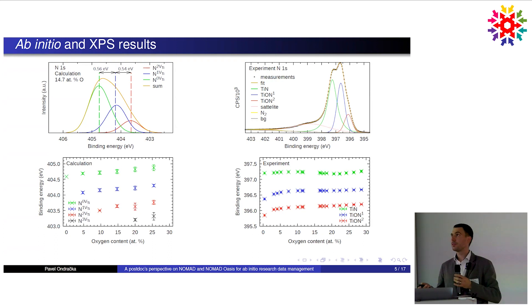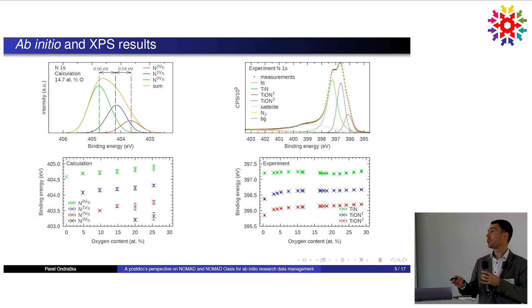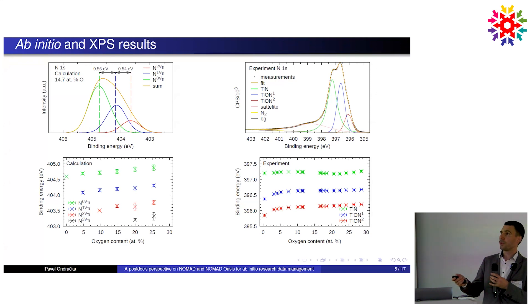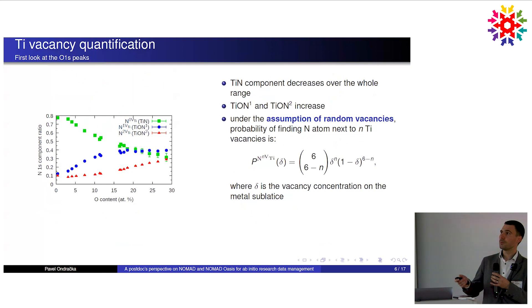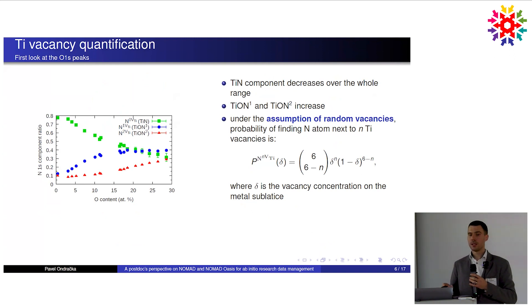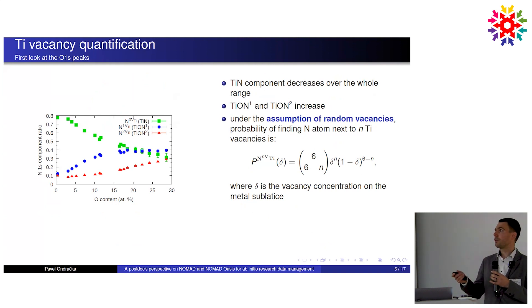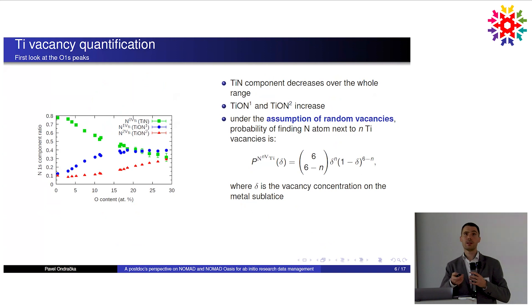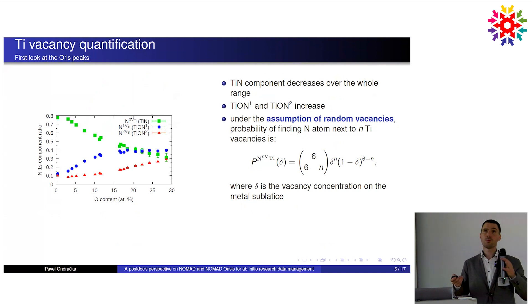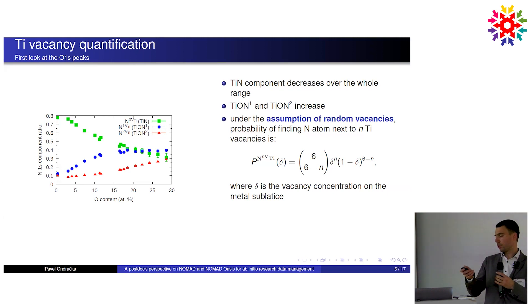This was a sign that what we are observing should be the same thing that was predicted. To be even more sure, when you plot the ratios of the peak areas of the three main peaks — corresponding to nitrogen with six, five, and four neighbors — you get a characteristic pattern. From simple combinatorics, if you have some vacancy concentration on the metal sublattice, the probability of a nitrogen atom having zero, one, or two vacancy neighbors can be derived directly from combinatorial numbers, and if you plot this as a function of vacancy concentration, you get curves that match the data.